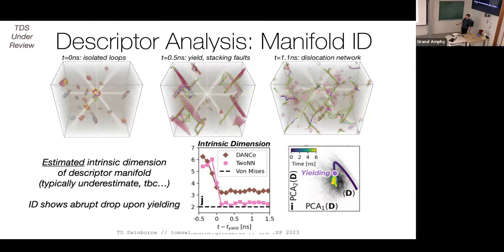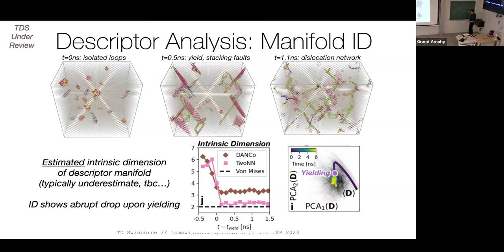The estimators tend to underestimate the true dimensionality when variances vary widely. What's interesting is that pre-yielding — where yielding is when I break away from linear stress-strain behavior, the transition from elastic to plastic deformation — the intrinsic dimension collapses, giving a much lower-dimensional embedding of the space. I can also see this clearly in a localization in PCA on this same trajectory. The representation is sensitive enough to all the coarse-grained properties I might want, but also captures more geometric ideas about these very complicated systems.